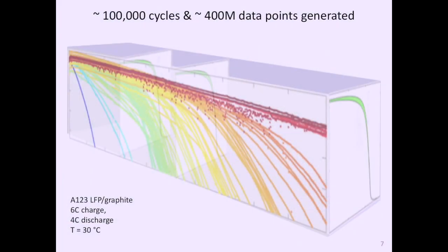And we're able to generate a data cube that is actually rather large. This data cube here is about 400 million data points. So we took about 100 batteries. We charge and discharge them in a variety of ways. We record temperature, voltage, resistance, current over time. Okay. So along the 3 axes, we have basically the cycle of the battery, the capacity of the battery, and the voltage of the battery. And we're able to record that.